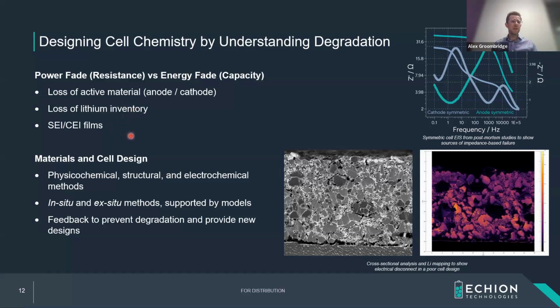Now, at Echion, we focused a lot on doing this, and I've got some examples. I won't go into much detail here of us looking at, say, bad examples. So cross-sectional results of a niobium-based electrode, showing an example where this hasn't performed very well, and we found that root cause, and now we've resolved it. And that's the sort of approach which we take at Echion, not just here's a good material, good luck, it's here is a good material, here's a good chemistry, and we understand how it works, so we can make sure that it works in that industrial use case for as long as possible going along.